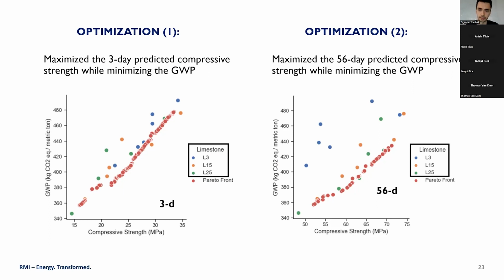In the trends, we realized that the algorithm kept suggesting high Portland cement and calcined clay contents to reach high early strength. But for late strength, it did not push using fine limestone or relatively higher calcined clay contents for 56 days. So in summary, for 56 days, the algorithm confirmed that we can use relatively coarser limestones and less calcined clay content than 30%. And we validated these results in the laboratory. The algorithm gave some compositions, and we selected some of them and tested them in the lab. We validated that the predicted compressive strengths were within 10% error of the measured compressive strength.